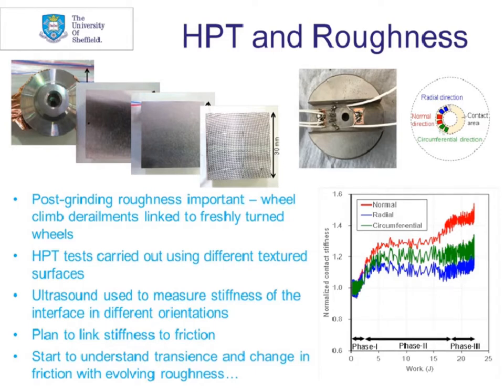that can lead to a problem. Again, we've gone back to our HPT testing now and combined that with our ultrasonic measurements to look at how the contact conditions vary when you have a rough surface. So we could look at the contact stiffness and see how that links potentially to friction, but also the real area of contact as well. So that's some very interesting ongoing work we have at the moment.